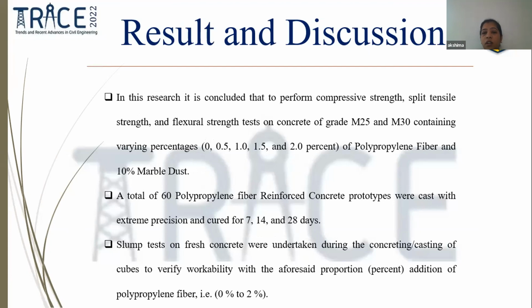What are the results and discussion we have kept? First, we have concluded results for compressive strength, split tensile strength, and flexural strength, all types of strength gained from these comparisons. For M25 and M30, we have used different percentages of polypropylene fiber: 0, 0.5, 1, 1.5 and 2, meaning we added it in 0.5% increments. We have taken 60 polypropylene reinforced concrete prototypes, meaning we made 60 cubes to check these, and tested them at 7, 14 and 28 days.